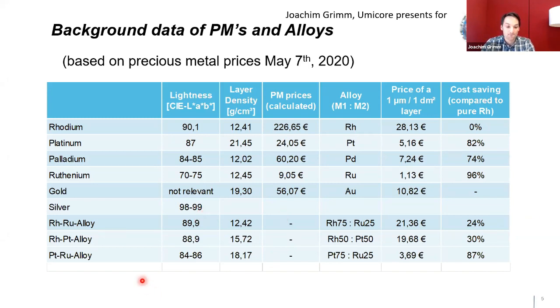And for another step of saving, which is at least the biggest step, if you have platinum mixed with ruthenium, you have sure not that wide a layer, you have a little bit more dense layer, but at the end, with a 75 to 25 mixture, your price of 1 micron at 1 square dm compared to the rhodium comes down to €3.69, so it's an 87% saving.